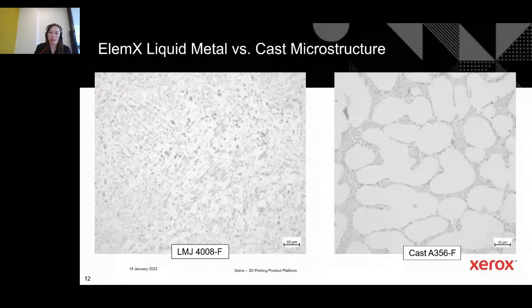So these are chemically identical, but on the left, we have a microstructure example of what's come off of our printer. And on the right, we have an example of what comes out of castings. And these are both in the as printed or as cast state, so they have not been heat treated. With this 4008 aluminum, the primary strengthening mechanism is from the precipitation of silicon and magnesium. So these darker particles you see interspersed on either the casting or the printed part, those are the silicon particles. So you can see on the printed part, they're very evenly dispersed, whereas in the casting, you end up with these sort of globs of the aluminum matrix. So the fact that it is so well dispersed lends itself to some strength in our application.